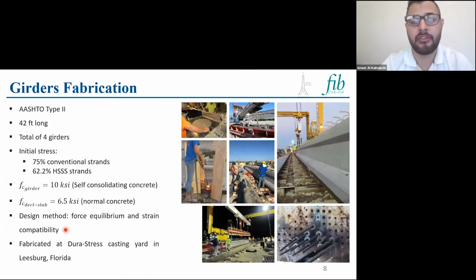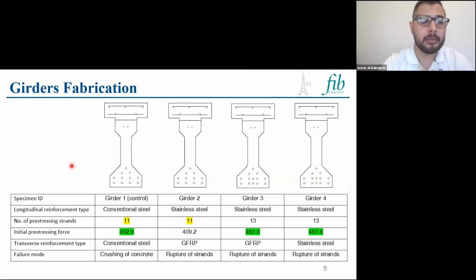The design method was force equilibrium and strain compatibility, because there are no design guidelines specified for the stainless steel strands. Those girders were fabricated at Dura-Stress casting yard in Leesburg, Florida. You can see here some pictures during fabrication. As I said before, we had 4 girders.